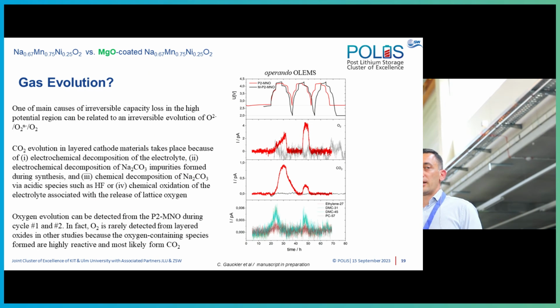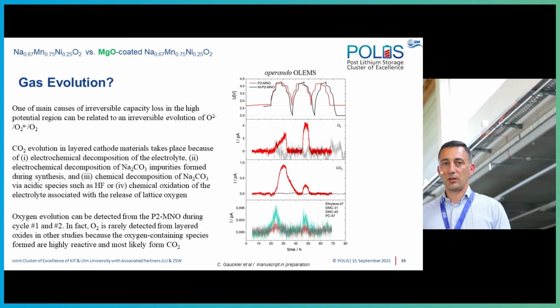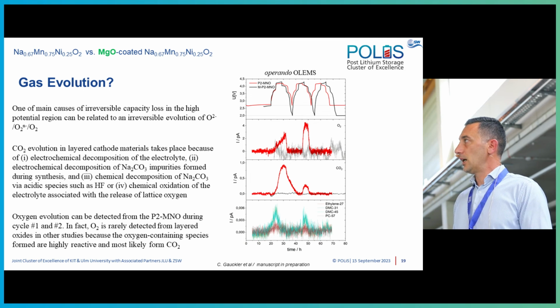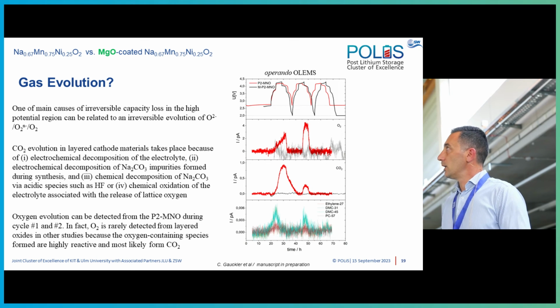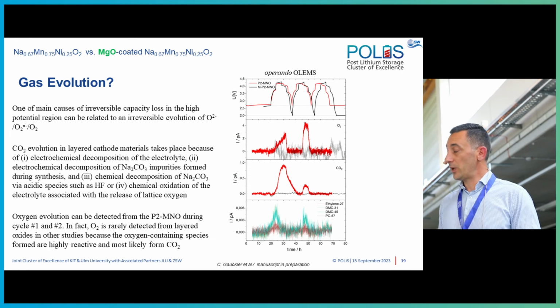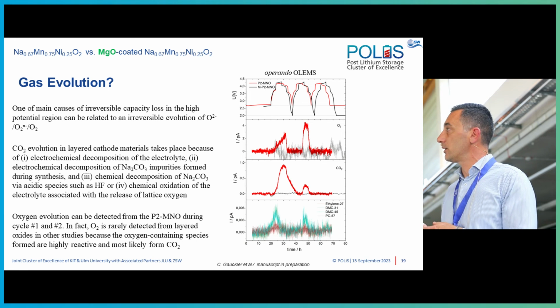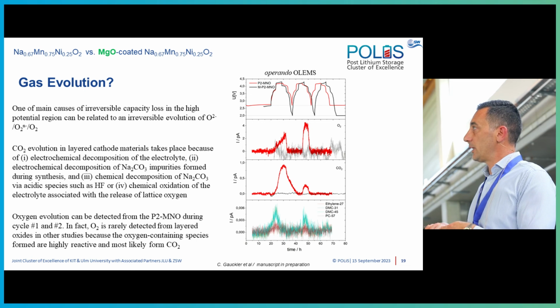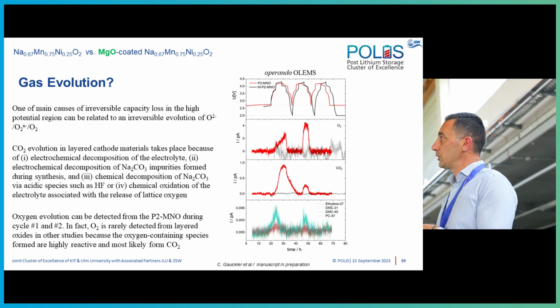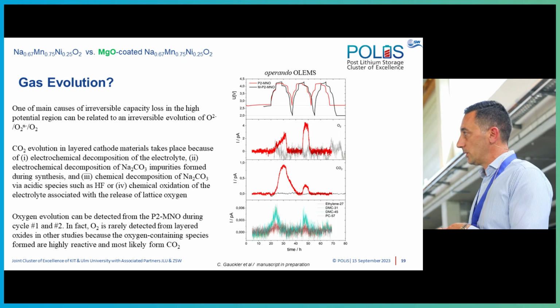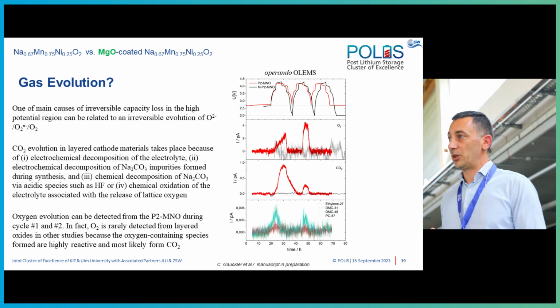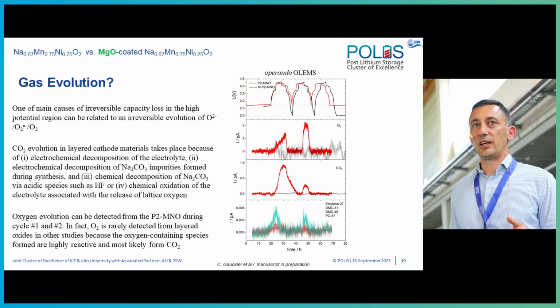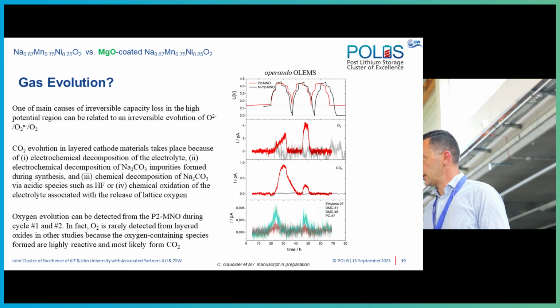As I mentioned at the beginning, for P2 layered oxides, one of the problems is that when you have the high voltage plateau, on top of the nickel 3 to 4 plus oxidation, you can have some oxygen evolution. So we actually looked at that with the Operando OLEMS. And what we have seen is that at least in the first 3 cycles, for the uncoated material, we have oxygen evolution, and in the first 2 cycles, CO2 evolution. Now, it seems that the magnesium oxide coating actually shut off any kind of gas evolution. So this was nice to see.